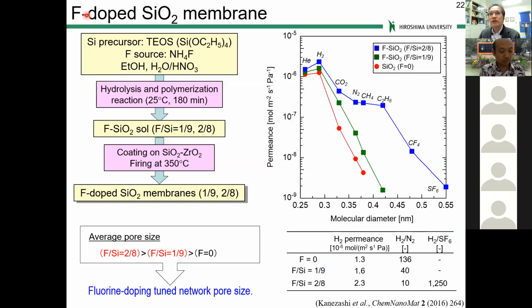Now let's move to the fluorine-doped silica. This is a simple process: we just add ammonium fluoride into the TEOS, and then hydrolysis and condensation. We have the fluorine-doped silica sol coated on a silica-zirconia intermediate layer to make the fluorine-doped silica membranes.